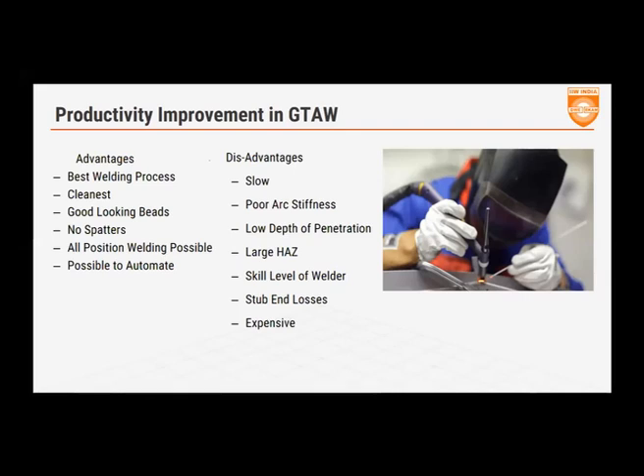At the same time, there are certain things that are always a restriction. That is, it's a slightly slower process, has poor arc stiffness, lower depth of penetration, higher HAZ, heat affected zone. Skill level of the welder, we needed little more. And one of the larger parts is stub end losses. So, the material you are using, if it's a fixed length, cut length part, the stub end of about 4 inches is lost. Thereby, the process tends to be termed as expensive. Can we make it more cost effective and faster?